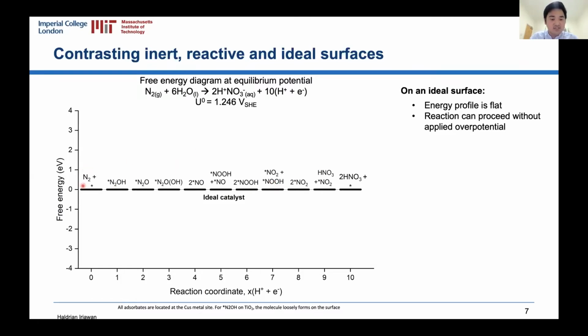So here are some of the results that I've collected. To start with, I've shown here the energy profile of an ideal catalyst. Here, the global reaction is a 10 electron transfer starting from nitrogen, our first step, into the product, which is our nitrates. The star denotes our catalyst, and the starred species denote reaction intermediates adsorbed on our surface. I've modeled here 10 steps of proton electron transfers, which correspond to the global reaction. And here at the equilibrium potential for our ideal catalyst, all the reaction intermediates are flat at 0, allowing our reactant and the product to be reversible with each other without any uphill steps in between. However, this is a hypothetical catalyst, and a real catalyst is not the case.